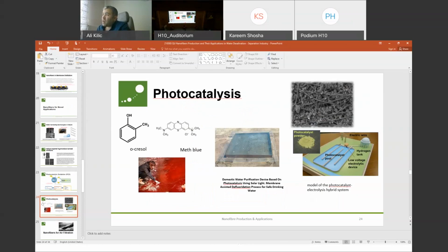Here, nanofibers are used as the carrier for these photocatalyst materials. You probably know that titanium dioxide and zinc oxide, these kinds of photocatalyst powders, are in powder form. So we cannot put them into the pool directly, because otherwise it is going to cause particulate contamination. So for that reason, we can store them over these nanofibrous surfaces and they are going to act again.